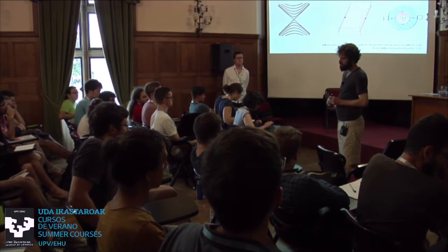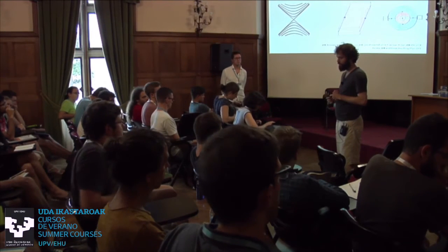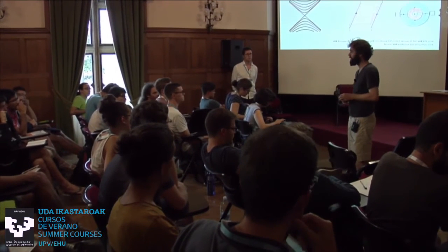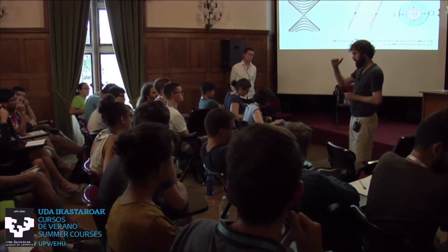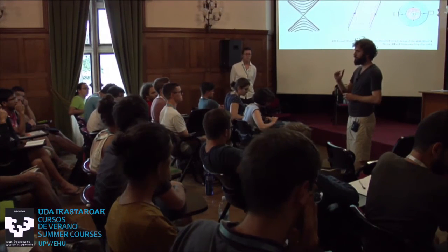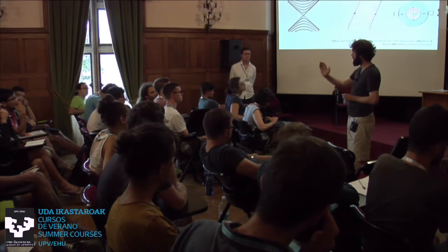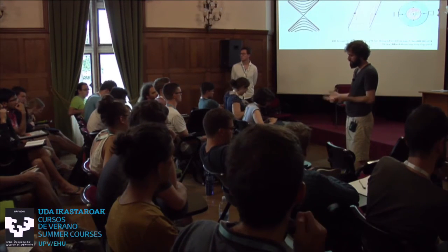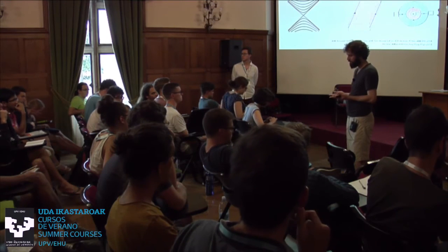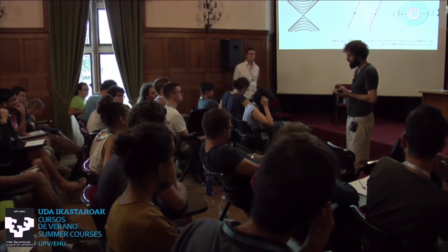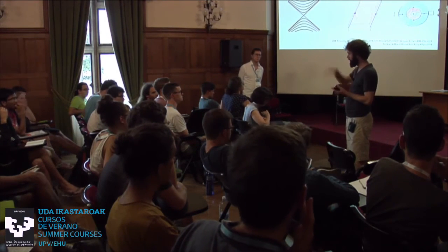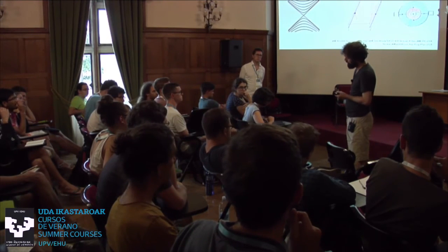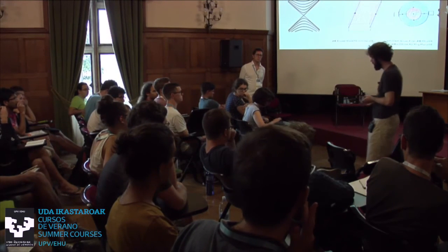And the main reason is, if I can qualify your question, if you wanted to go to the regime where you could see Majorana physics, then you need to reduce the number of modes such that the signatures of the Majorana mode dominate your signal. But in most of the materials, it's hard to control the growth such that you can tune the chemical potential very close to the Dirac point.